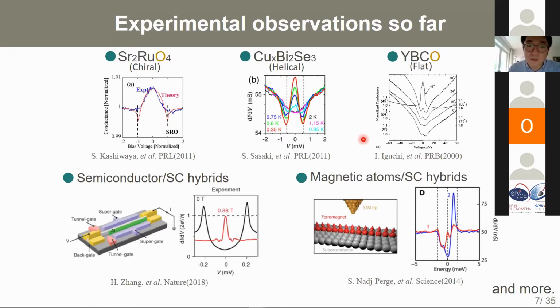tunneling spectroscopy. For instance, strontium ruthenate is believed to host time-reversal-symmetry-broken unconventional superconductivity. And in that case, in a clean two-dimensional electronic structure, we can expect chiral edge states protected by a Z topological invariant. And actually, a planar tunneling spectroscopy experiment shows the zero energy peak structure.